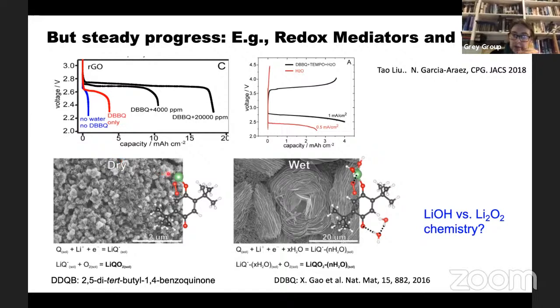One of the practical ways of doing this is to use what's called a redox mediator. This is an example of a quinone. You can take a quinone functional group with carbon oxygen double bonds, and you reduce them on the carbon electrode, and then they go on and react with the oxygen. So this is the picture of the oxygen here. Then you can essentially get the chemistry to work in solution so that you can build up much larger deposits of lithium peroxide. And then you can come in with another redox mediator, TEMPO, which is a nitroxide, and you can use the nitroxide to oxidize the lithium peroxide, and you can reduce the overpotential. This is work of ours fairly recently, where we were showing that you could also introduce water, which would improve the solubilization and improve the capacity.